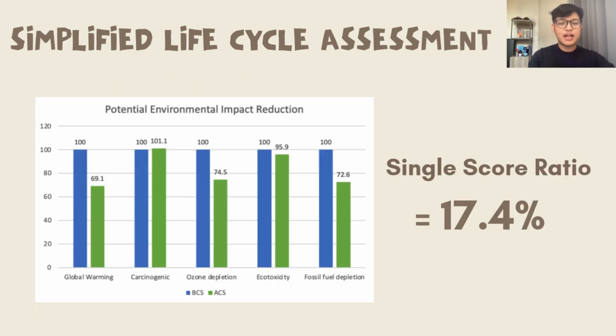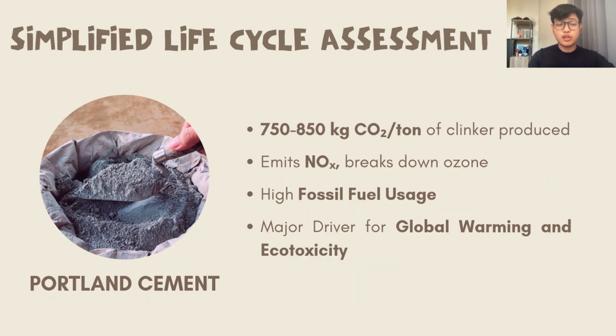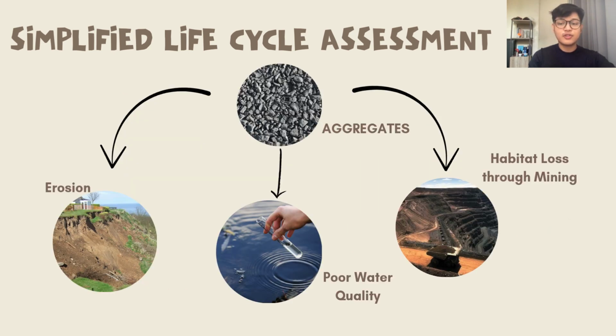In the Ecoconcrete calculator results, the ACS mix showed a single score ratio of 17.4% in environmental impact compared to the BCS. Portland cement was the largest contributor to environmental harm, releasing up to 850 kg of carbon dioxide per ton through calcination and high-temperature kilns. It also emits nitrogen oxides, which contribute to the ozone layer breakdown, and requires significant fossil fuels. Aggregates added further strain through habitat destruction and erosion.